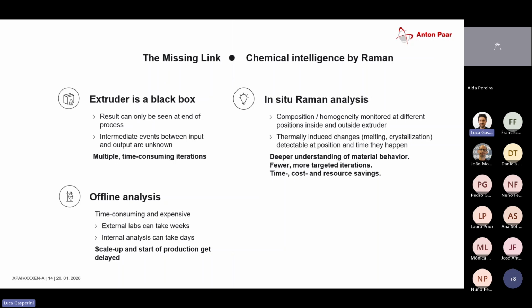Why do you use Raman here instead of, for example, FTIR? The problem with FTIR is that the light source is only infrared light, so the power of the light source is not as high. So you have a rough time using FTIR on an extruder just because of the light source intensity. This is why with Raman you have a class 3 laser, so you can also have a 3 meter long cable. You do not lose any intensity of the light source. That's why you use Raman.